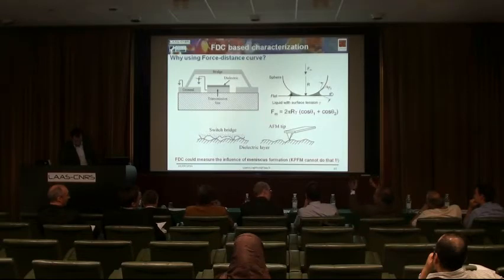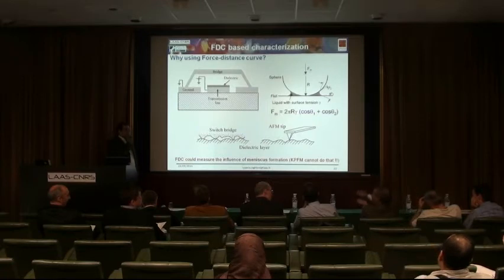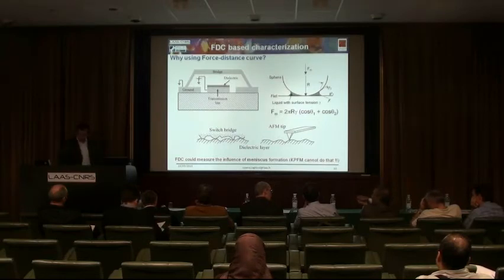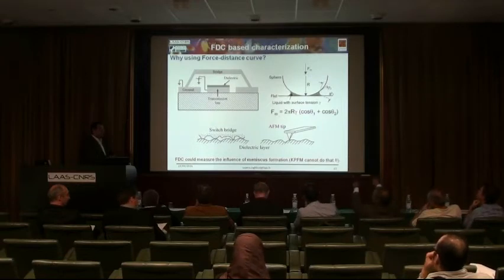And what the concave shape does is that the pressure inside the meniscus is negative, less than ambient. That leads to an intrinsic attractive force. If you were to plot this cartoon for surfaces which are hydrophobic, they'll be convex shaped. There'll be a positive pressure, which is going to push the two surfaces apart, so you'll have negative adhesion. If the surface is hydrophilic, then you're going to be pulling them together. I think this also comes from the definition of the contact angle itself. With simple physics you can derive that the shape has to be concave.